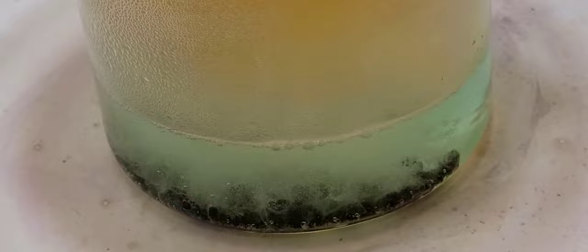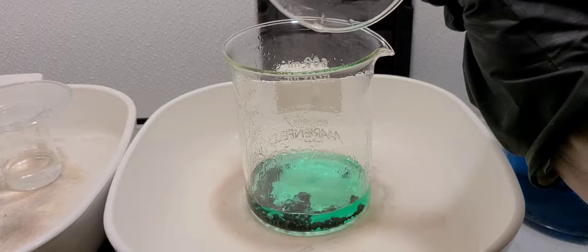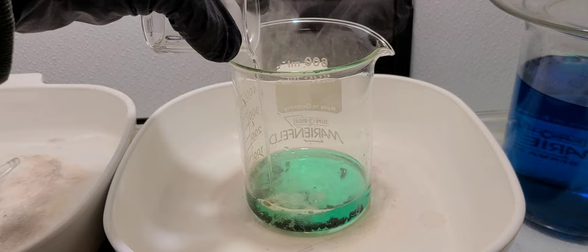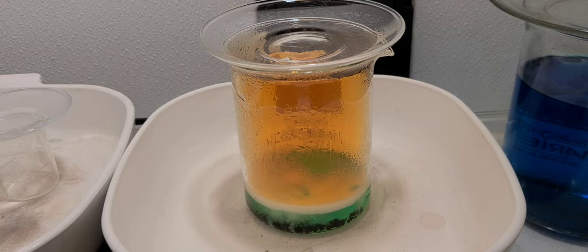You can see it's changing colors. The darkness is somewhat of the silver oxides, and it's also the gold being exposed. As you see the solution turning green, that's that mix of silver and copper — those are the predominant metals we're looking at. Our reaction slowed down, so I just added a bit more nitric acid. Obviously it fired back up, but I'm going to keep going until it doesn't react anymore.